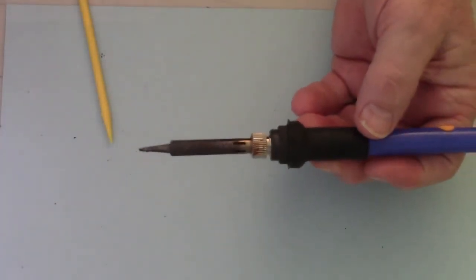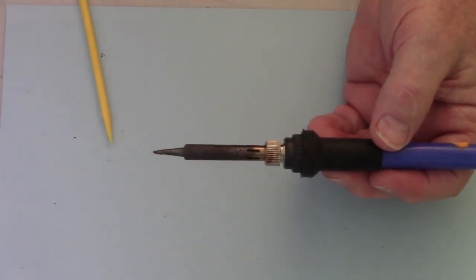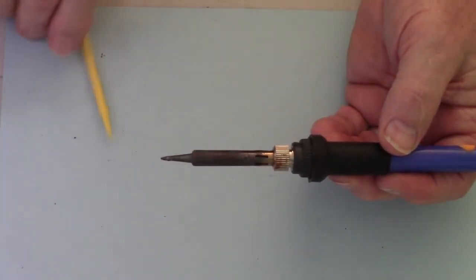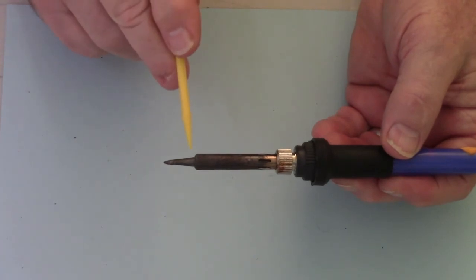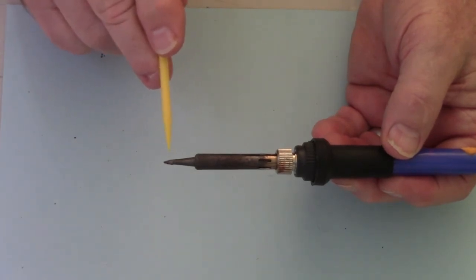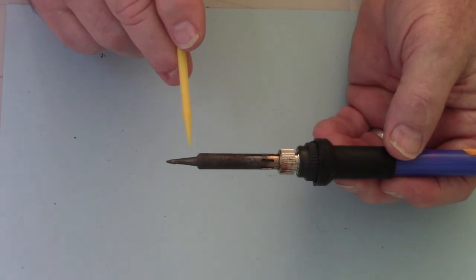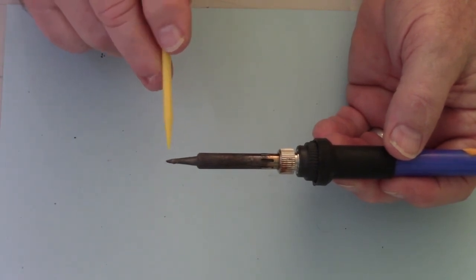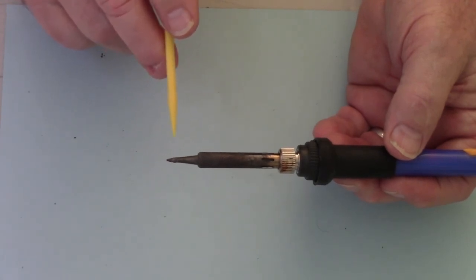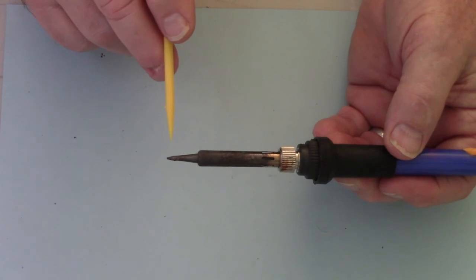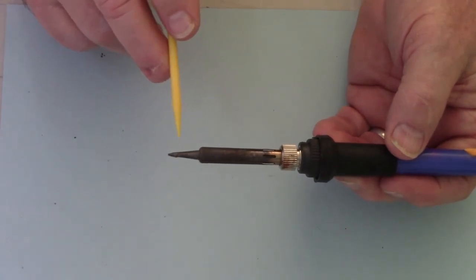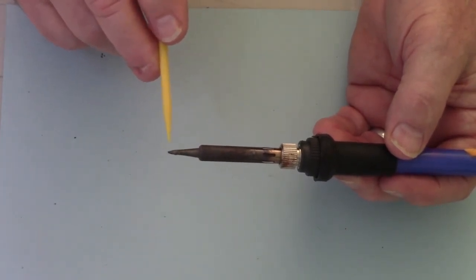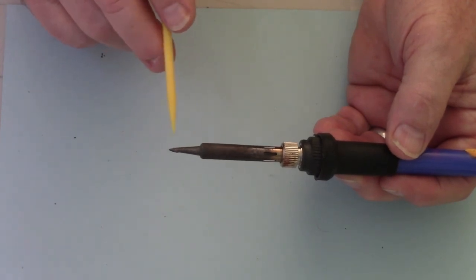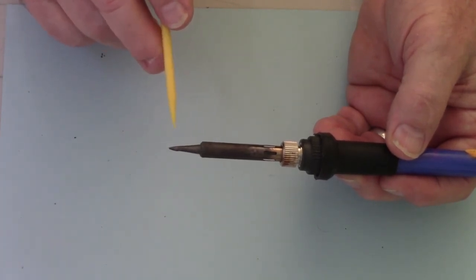One is one that I had in one of the classes that I teach, and you can see that we're pretty dark up on the tip here. Especially what we want to look at is right at the tip. That's a copper tip that's on here, but it has an iron coating over the very tip of it. The reason is that copper transmits heat very readily, so it is an excellent metal to have the basic tip made of, but it is very susceptible to wear, and in using it, you're going to pit it quite easily.